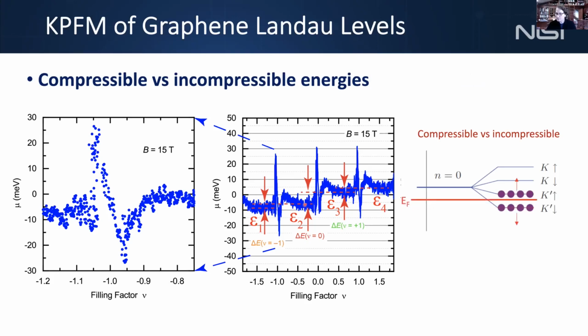Traditionally, transport measurements measure the mobility gap, where they put the Fermi level in between the Landau levels, excite carriers, and measure an activated temperature-dependent resistance change, and they try to extract the gap that way. When you do this, you actually polarize. When you put the Fermi level here, you can polarize the Landau levels, and that will add an exchange enhancement to the energy gaps and actually open them up. And that's what gives rise to sometimes these big excursions that you see in the chemical potential, exactly at these integer filling factors. It's when you get this exchange enhancement.